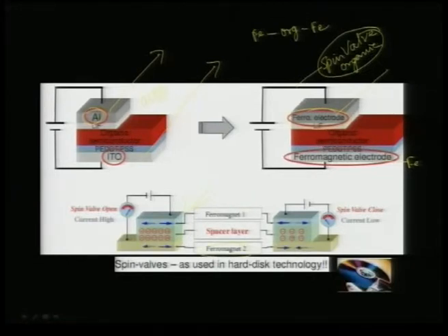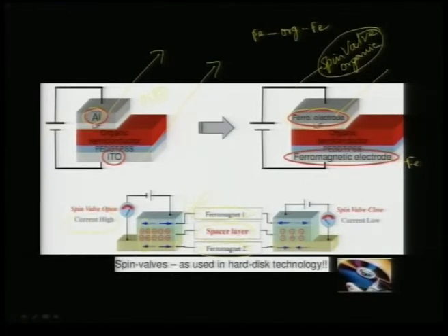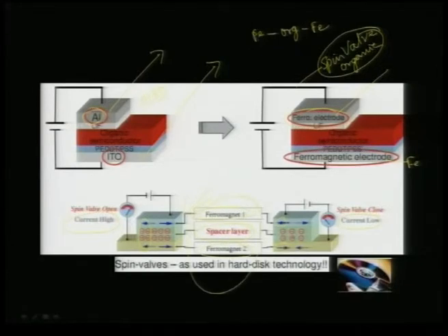You are essentially making an iron-organic-iron electrode device where you can look for spin valve operation. This is the typical way to cartoonize the spin valve structure involving an organic layer where you have ferromagnetic-1 and ferromagnetic-2. When the ferromagnets are aligned, there is more electron mobility — a current-high situation when the spin valve is open. If they are anti-parallely aligned, you have current low; so with a ferromagnetic–organic–ferromagnetic device you can bring about a spin valve response using organics.